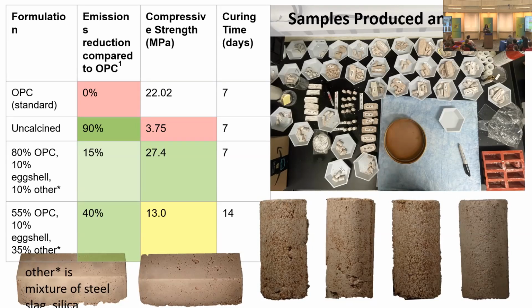We've been collecting eggshells in our homes, bringing them to the lab, grinding them, calcining them, and turning them into concrete. We are calcining the eggshells, but at a significantly lower temperature, only around 900 degrees Celsius. We've used this cement to replace OPC up to 45% with up to 40% emissions reductions. And we've also been able to reach strengths above just OPC alone. So this is really how we've been approaching it.